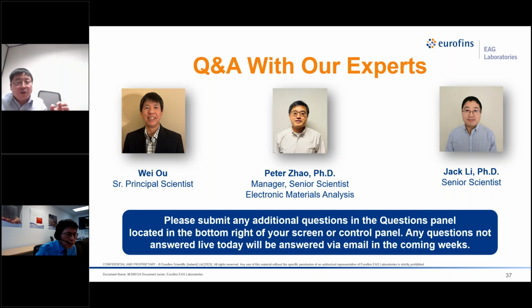For silicon carbide, the difference is that when you implant it, it will not diffuse. This is different from silicon. For silicon, you implant it and anneal it at high temperature, so the aluminum or nitrogen will diffuse, and the profile will be different from the one without annealing. But silicon carbide is hard, and the diffusion is very low. For the SIMS measurement, it will not affect the precision. Generally, whenever the doping level is low, then because of the background contribution, it will affect the measurement.